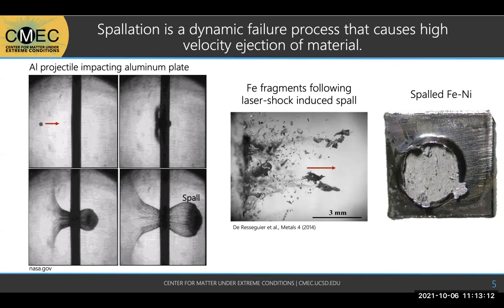But the images on the right there are newer, higher definition, and you can see that there's a lot of fragments coming off. The spalled iron nickel that I have is actually one of the recovered samples from my experiments, and you can see how that crater just kind of ejects off the back. And in both of these cases on the right there, the velocities were on the order of kilometers per second, and so that's incredible speed that can really damage anything that it impacts. So obviously this is all really interesting, but why does it happen? So next slide.